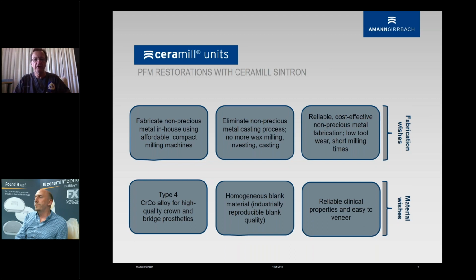and it's like this black was trying to grow through. Well, then we realized that if we just put a coat on to start with, then it stops the growth. And by the time you put the second coat of opaque, it's gone. And so that's when we started not degassing the chrome itself. And so again, all we do is sandblast 50 micron and steam it, and then immediately put the opaque on.